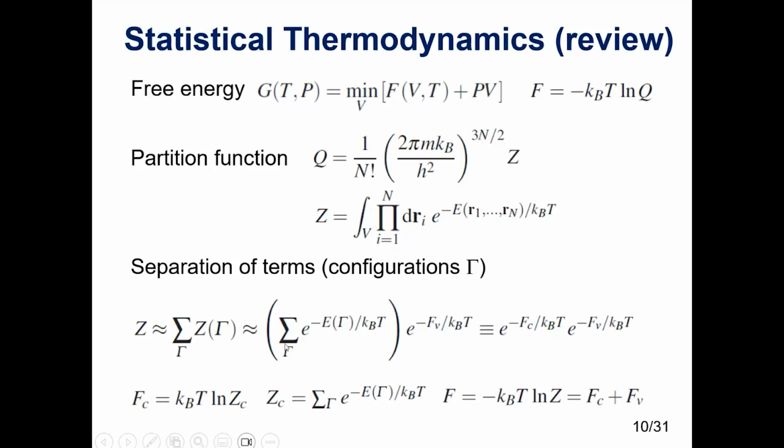And so one contribution to the partition function is a sum over these chemical configurations of the Boltzmann factor for the relaxed configuration. But of course, in these integrals, we have contributions not only from the precise relaxed configurations, but also from small neighborhoods around. And these small neighborhoods correspond to the atomic vibrations. And so there's going to be a correction to this first term that I call the vibrational free energy.